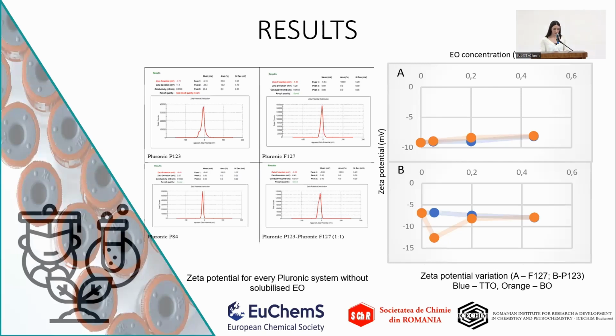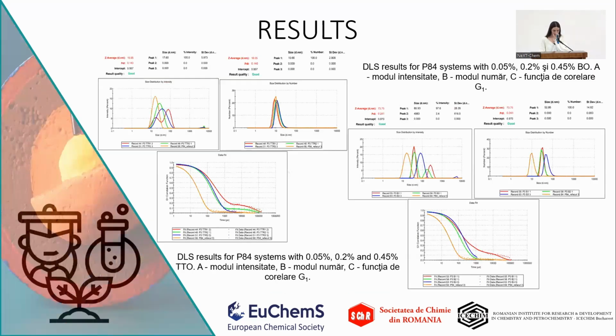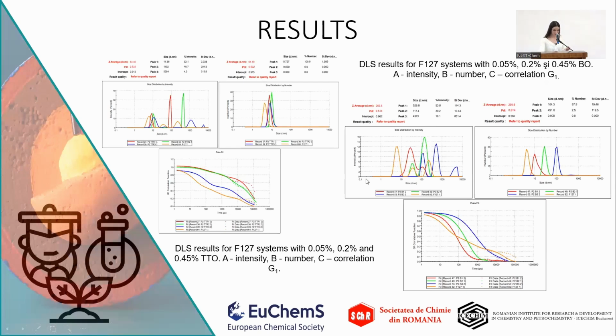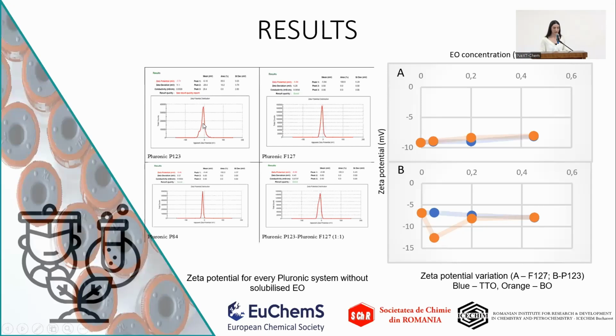Next, we measured the zeta potential for every pluronic system without solubilized essential oil. These values of zeta potential were actually a bit small. That implies an instability of the system of the actual aggregates, which is also confirmed by the existence of some bigger aggregates right here. That means the dispersion is unstable.